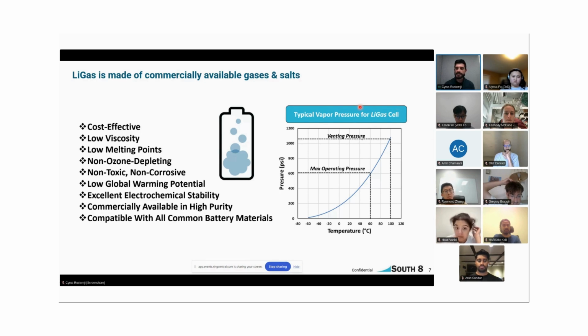Here on the right is a standard vapor pressure curve for a typical electrolyte that we use today. At room temperature, we're operating right around 300 psi. And around 100 degrees Celsius, we are looking to vent the cell. That allows us to operate with a good buffer between 60 degrees Celsius, which is the max operating or storage temperature, and where we hit thermal runaway, closer to 110, 120 degrees Celsius, which is generally where you see things really take off. So by venting the cell at 100, we can cut off that thermal runaway reaction, but still maintain very high performance in the cell applications and with our customer requirements.